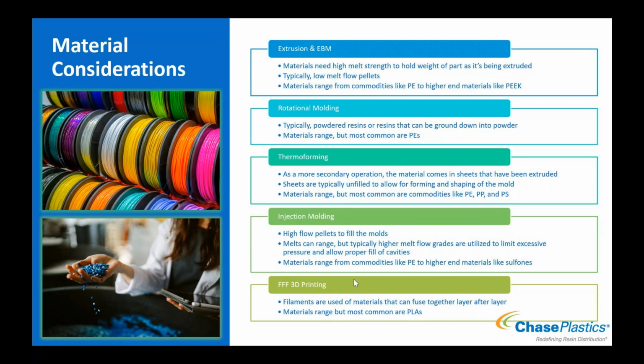Then thermoforming, as we mentioned, because it's kind of your secondary operation, you have to have extruded sheets first. These are going to typically come in unfilled variants. You're not going to use a filled material for these because it's going to be really difficult to form or get into a shape if you've got really stiff glass in the material. So with unfilled products, the most common are going to be your commodities: your polyethylenes, your polypropylenes, your polystyrenes. These are the most common materials used in those applications. Again, you need them in sheet form, so you've either extruded the sheet yourself or you buy the sheet to be thermoformed.